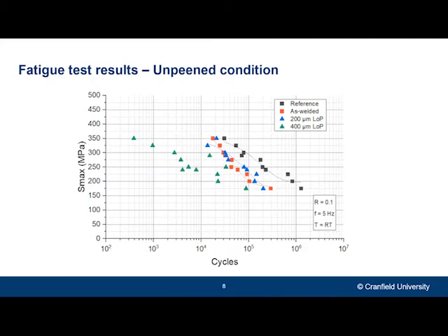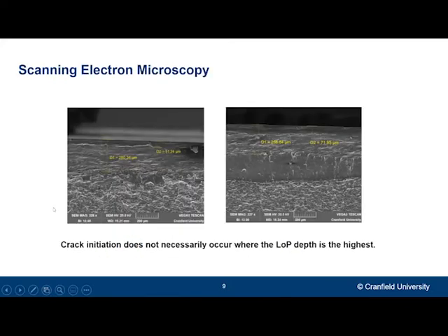So what this is telling us is that the 400 micrometer defect is clearly acting as a crack initiation site, while for the 200 micrometer defect, the stress intensity factor at the defect tip is not dominant when we compare it to the effects of the microstructural and residual stresses on the shoulder side, which is typically the failure location.